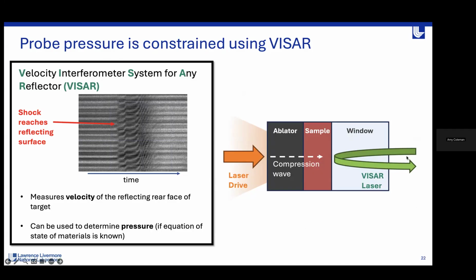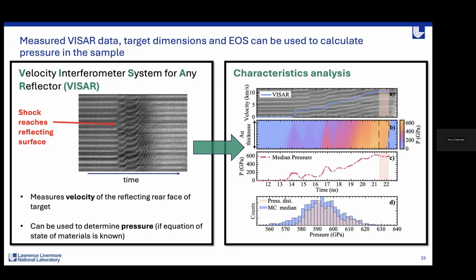So during the experiment, the VISAR laser comes through. It is transiting our transparent window on the rear surface of our physics package, and it is reflected from our shiny sample surface. If your sample is not something that's shiny, that's okay. You can add a small shiny flash coating layer to that, but it does have to be reflecting this laser light. The data that is collected is sort of streaked data, and you can see that as the shockwave reaches this interface between the sample and the window, we've got a motion in these fringes, right? And this is a measure of the Doppler shift of our moving target. By analyzing the motion of these fringes, we can interpret a velocity in our target.